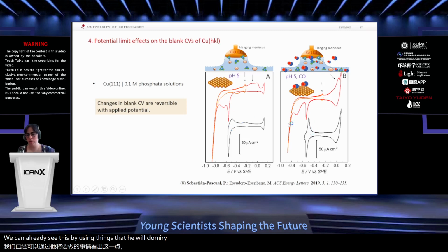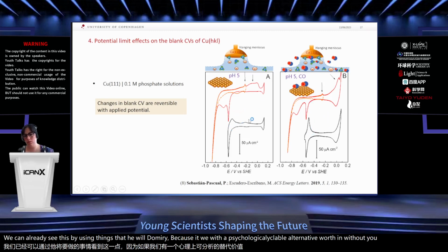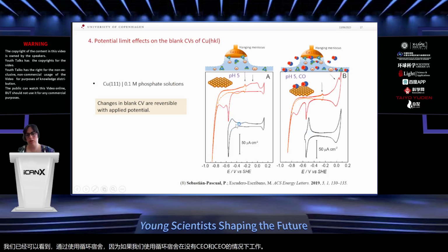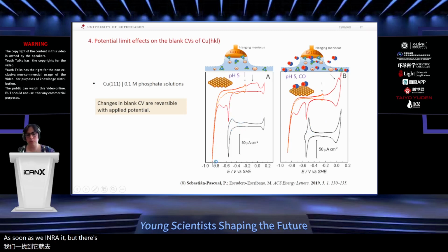Because if with the cyclic voltammetries, both without CO and CO in solution, as soon as we increase the potential limit to more negative values, what we see is that these features in the cathodic scan are completely shifted to more positive values. So it's clear that something is happening, maybe a change on the surface structure or just a change on the copper electrolyte interface.